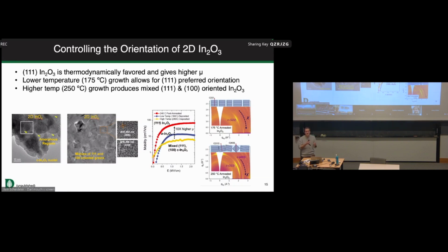Two, the orientation matters. So indium oxide's cubic crystal system, it has essentially the lowest energy facet if it grows along the 111. It also happens to have the best electronic transport properties. So you can move electrons the most efficiently. You can mitigate a lot of the other scattering mechanisms. So we want 111 oriented indium oxide. It turns out the way to grow that is actually if you can deposit it at low temperatures and then crystallize it from the solid phase.